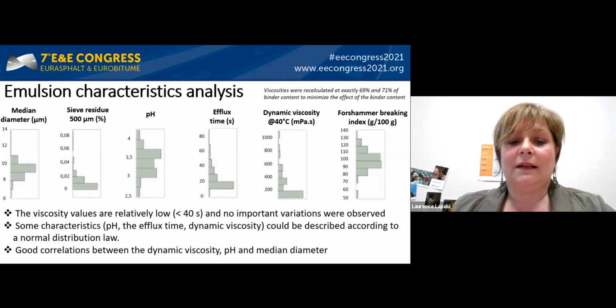The statistical analysis has highlighted that some characteristics, that are the pH, the efflux time, and the dynamic viscosity, could be described according to a normal distribution law. And the statistical analysis has also highlighted that three variables of the emulsions, that are the dynamic viscosity, the pH, and the median diameter, can summarize the measures carried out on the emulsion. So that's why for the next slide, I will be focused on the pH and on the dynamic viscosity.